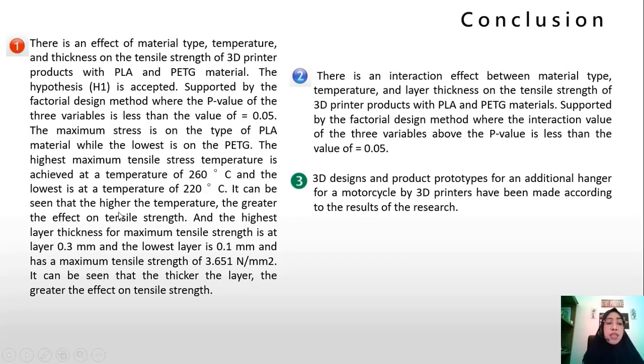It can be seen that the higher the temperature, the greater the effect on tensile strength. And the best layer thickness for maximum tensile strength is 0.3 millimeter and the lowest is 0.1 millimeter, with a maximal tensile strength of 3.651 Newton per square millimeter. It can be seen that the thicker the layer, the greater the effect on tensile strength.